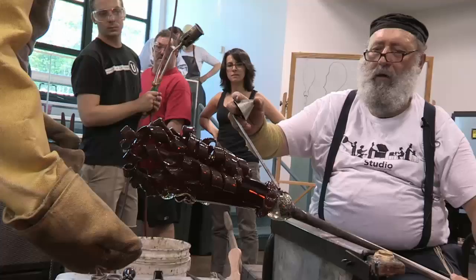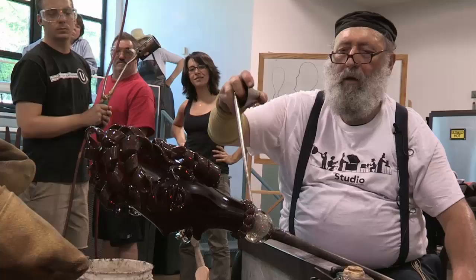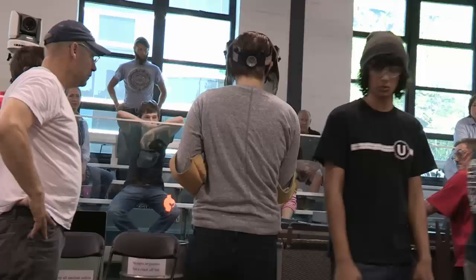Emily McBride is suited up with high temperature Kevlar gloves and a hood shield because the heat that comes off of this is amazing. She will be gently loading it into an oven that's roughly 900 degrees, where it will sit potentially 10, 15 hours to cool down slowly to room temperature.